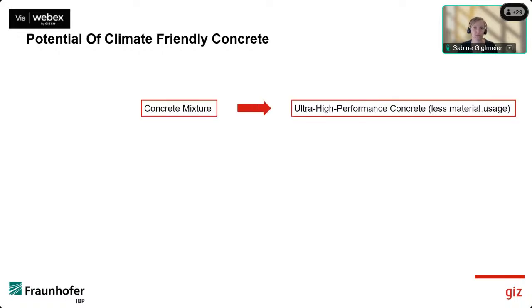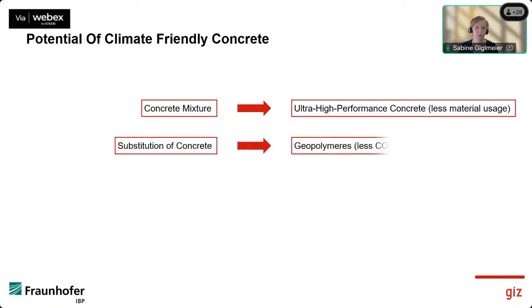We have different options to improve the carbon footprint of concrete. On the one hand, we could change the concrete mixture. We could, for example, use ultra-high performance concrete, and so we need less material. The next option is we could substitute concrete by other materials with comparable properties, but lower CO2 emissions during production. For example, with geopolymers, which have very similar properties, but they do not need any cement and need much less energy during production.